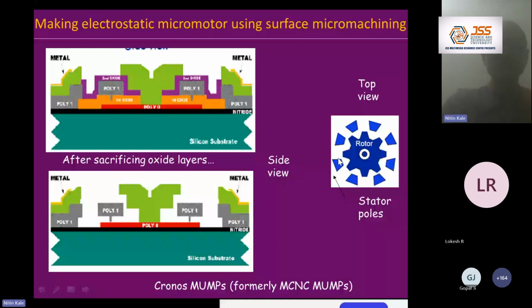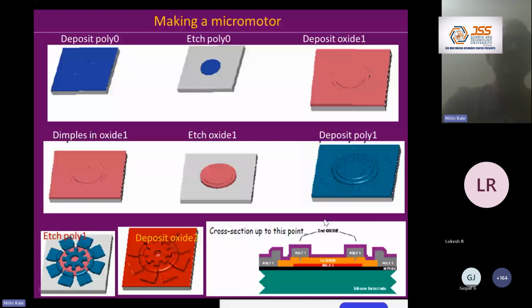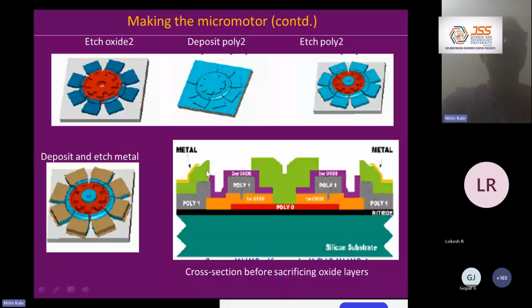This is that rotor part which I was talking about. Okay. So how it progresses is, you have a starting material, you deposit poly 0, you pattern poly 0, you deposit oxide 1, you create what are called dimples in oxide 1. These dimples are certain features which prevent stiction from happening. Okay. Then you etch your oxide, you deposit poly 1 layer, you etch poly 1 layer into shape which is like this, you deposit oxide 2, then again now your cross section is looking, let's say, something like this. You have your oxide 2, second oxide is like this, this one is now looking like this. The rest of the etchings we have already carried out.